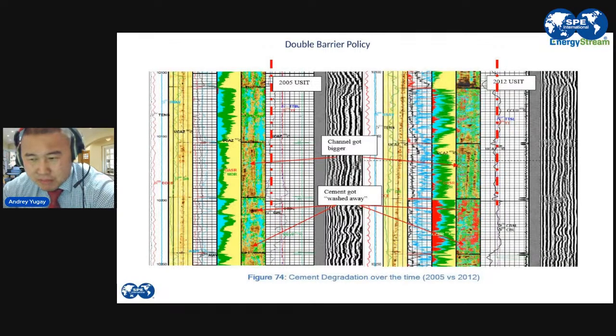However, if we punch a hole here in the casing, let's say at this interval, just at the top of the liner, top of this log, it might be that the leak rate will be lower, because all this cement, all this 9 or 10,000 feet of cement, chokes the flow. But if we go deeper, we have less choke, so less friction. So we're going to have a higher leak rate. And definitely, if I make a hole somewhere across the gas invasion area at the bottom of this log, on the right side, you can see, definitely the leak rate will be higher than it was above the small cement ring, because the cement ring works as a choke that restricts the flow.